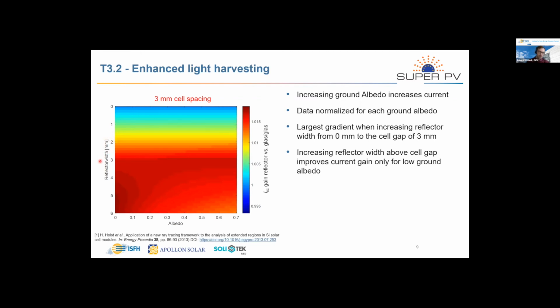Here, on the one axis, we have the size of the reflector varying from 1 to 6 millimeter. And here at the bottom axis, we have the ground albedo, which is varying from 0 to 0.7. And the color coding here indicates the gain in short circuit current for a module with a reflector compared to a module which uses only a glass-glass layup, so a simple bifacial module. So when you have a reflector size of 0, we have no reflector, which means that we have a bifacial module. So the gain here is blue, which means that we have a gain of 1.